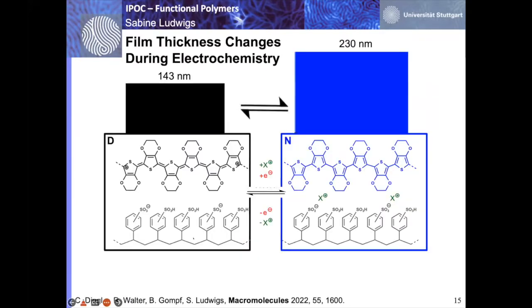What one also learns when looking further at the PEDOT:PSS material, and the method of choice we took there is spectroscopic ellipsometry. We saw that when we make films on the surface and we switch essentially the electrochemical doping potential between the doped and the neutral state, we also see film thickness changes. So you see the doped state here during an electrochemical experiment amounts to roughly 140 nanometer. In the neutral state, the film increases to 230 nanometer.